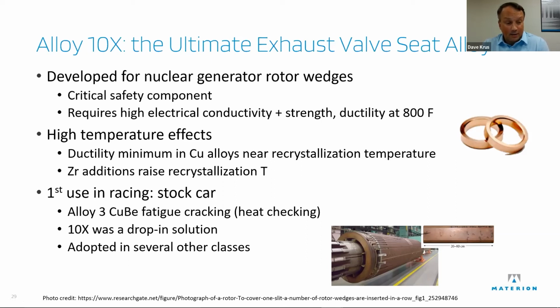And it had a minimum ductility requirement, a minimum strength requirement, also with the thermal conductivity, and in this case, electrical conductivity, which are related. So what happens in all copper alloys, or precipitation hardened copper alloys like these, is as you get close to something called the recrystallization temperature, and that's a whole metallurgical class I don't think I could ever even give, but as you get closer to that, the ductility goes down. You would think as you heat it up, it gets wobblier and softer. Well, it actually gets more brittle for a start and then goes through a transition. So if you put in a little bit of zirconium, you raise that recrystallization temperature to a higher one and allow the metal to be used at a higher temperature.